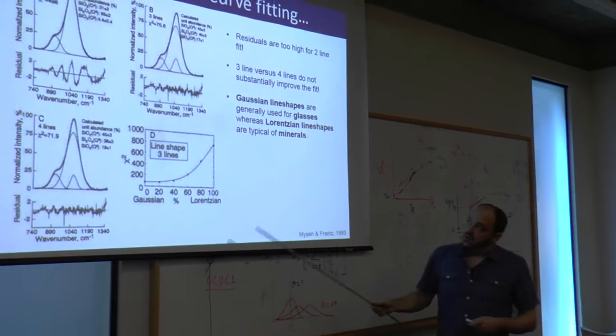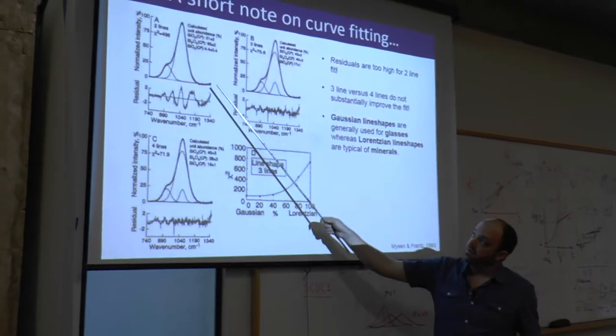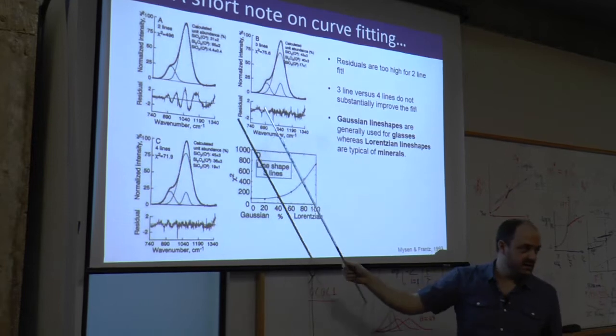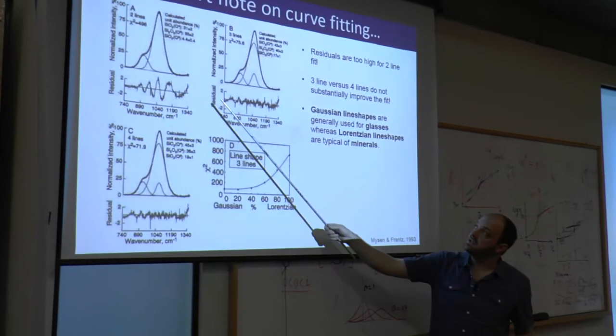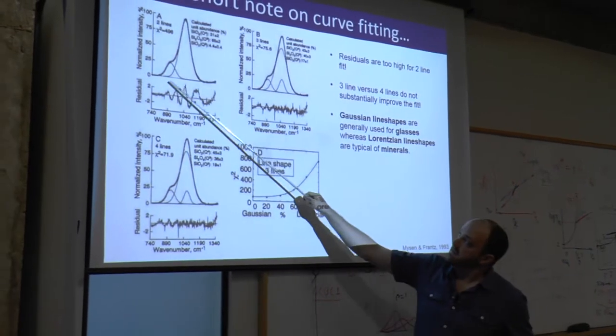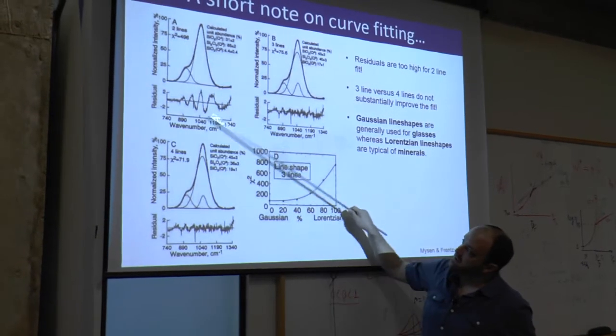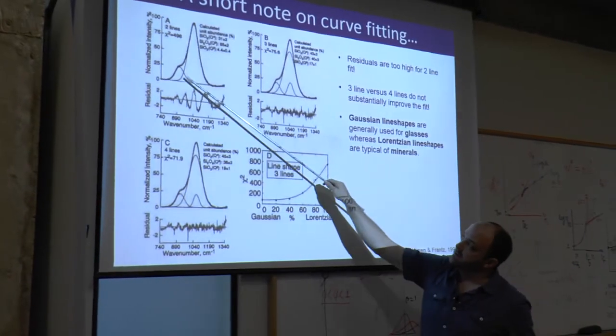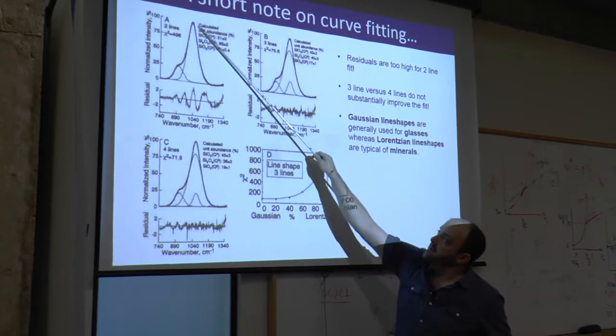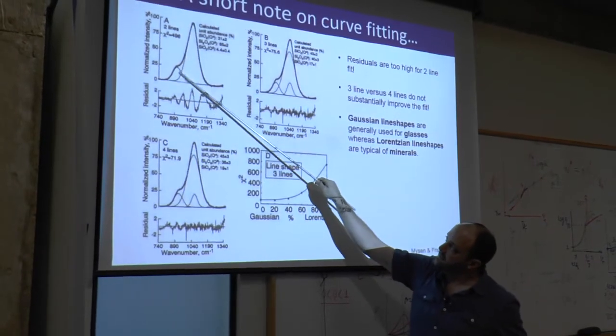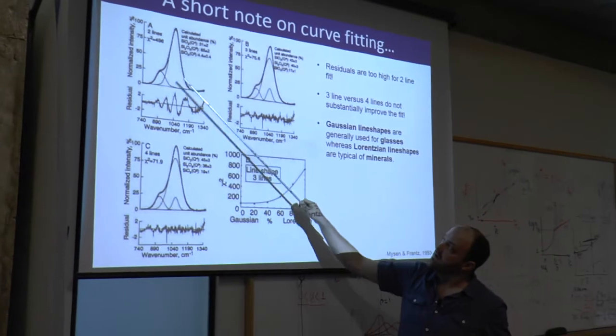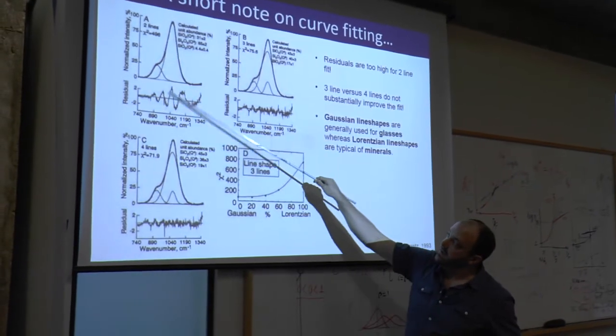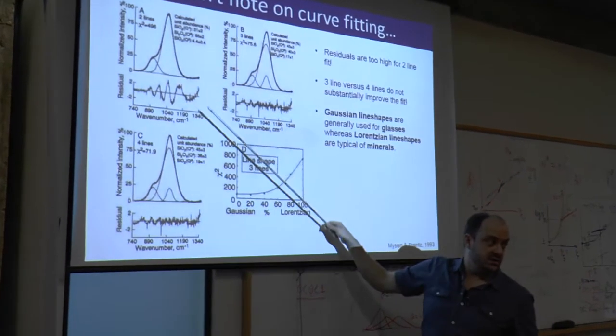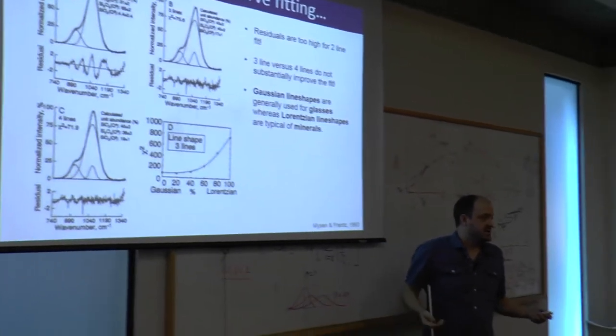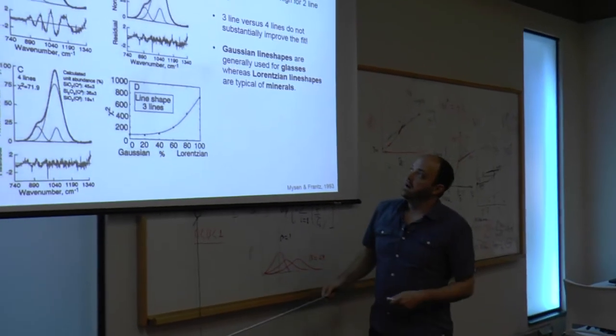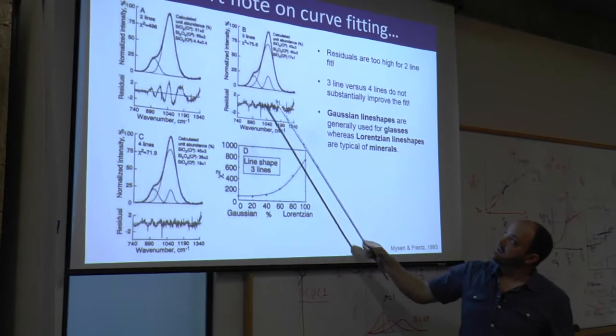If you try the same spectra with a couple different lines. So this is an old study that gets a lot of citations. It's curve fitting for glasses. If you take this envelope, which covers a couple hundred wave numbers, you can see that there's this shoulder and a main peak here. If you have just two peaks under this curve, you can see that the residual here is quite erratic. It's quite large. So chances are this tells us that there's another peak required to fit this envelope.